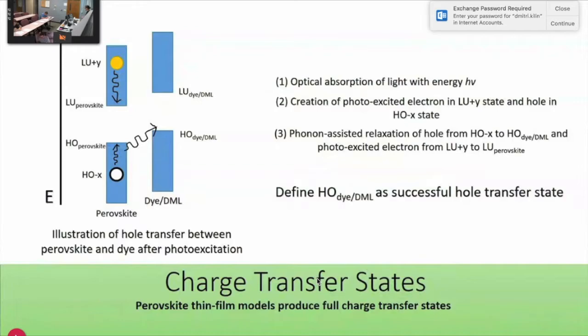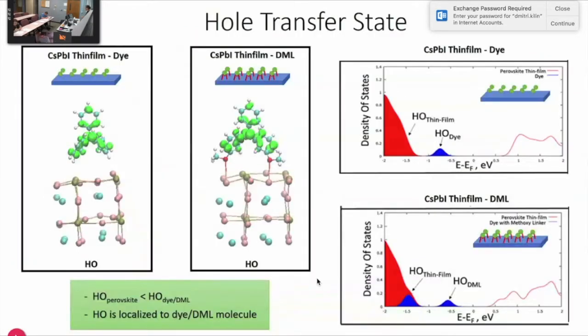And then just to illustrate these charge transfer states, we show the orbitals to the left, and on the right is the density of states for each assembly. The top one is a thin film with the dye, where you see that the electron density is partitioned between the perovskite, which is the